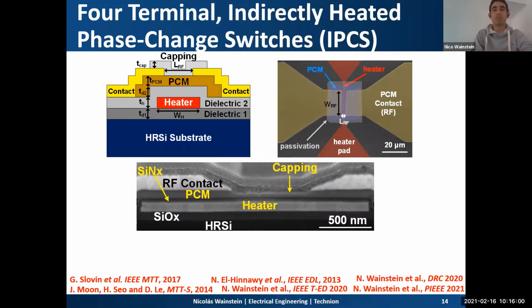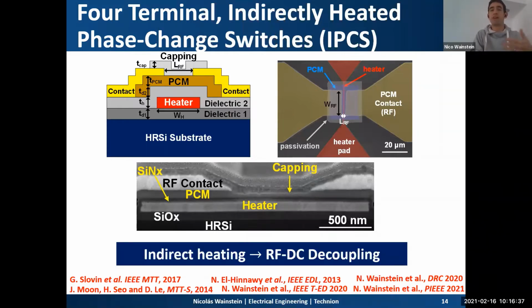The IPCS consists of 2 RF ports in line with the PCM, as you can see here, separated by a very small gap, and 2 terminals for the thermal actuation, top and bottom, using an embedded heater. This heater runs transversely to the direction of the RF path under the PCM. The heater and the PCM are separated by a thin electrically isolating film, the dielectric 2 here, that is usually silicon nitride, and therefore there's a built-in RF DC decoupling.